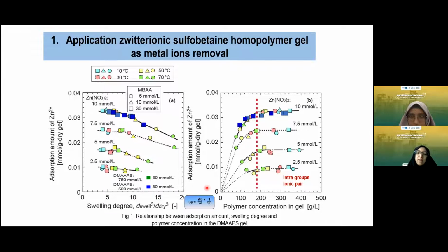By converting the swelling degree to polymer concentrations in gels, by using this term, we can use the second graphics. It can be seen that from 0 to 180 gram per liter, the absorption amount of zinc ions increases gradually and remains unchanged with increasing polymer concentrations higher than 180. The remaining absorption amount can be explained due to higher polymer concentrations. The association is quite strong and dominated by the intragroup association and also intrachain associations.